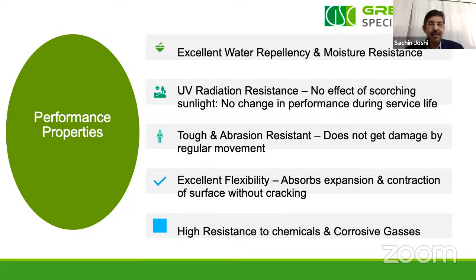Then there is excellent flexibility, yes, because of expansion and contraction: as temperature increases, the substrate expands, and as temperature reduces, the substrate contracts. And this expansion and contraction is not a one-time process. It's 24/7, 365 days. So it shouldn't be that for the first 3 months it is going good, and after 6 months it's reducing. So this technology gives 10 years, 15 years retention of properties against all the environmental abuses, and very high resistance to chemicals and corrosive gases. So the second circle, enhanced performance, we have achieved.